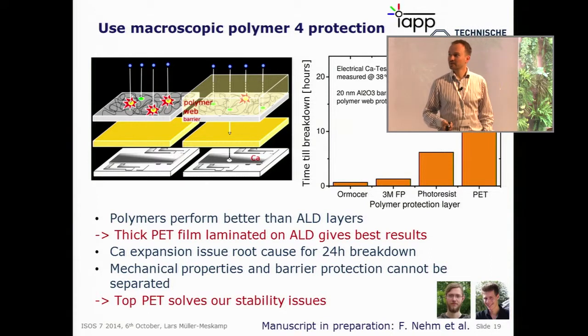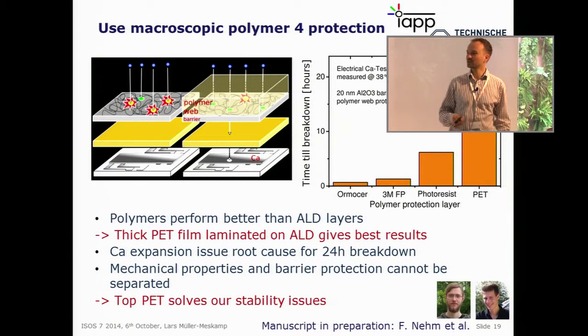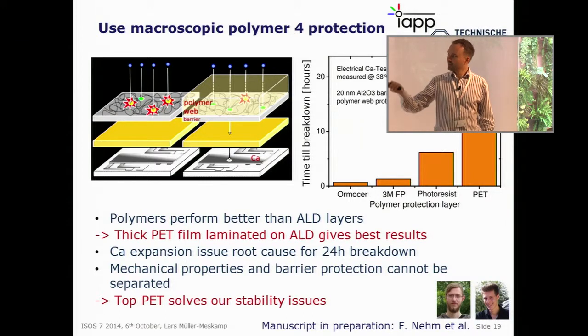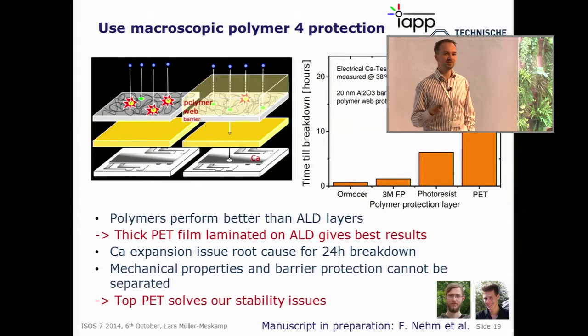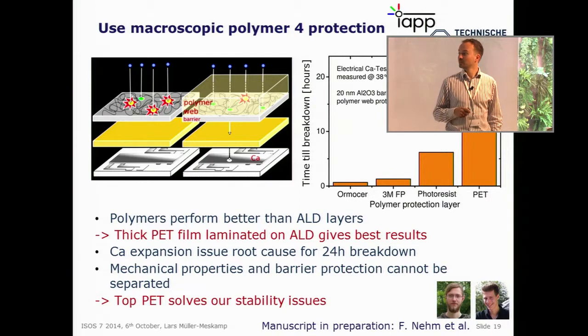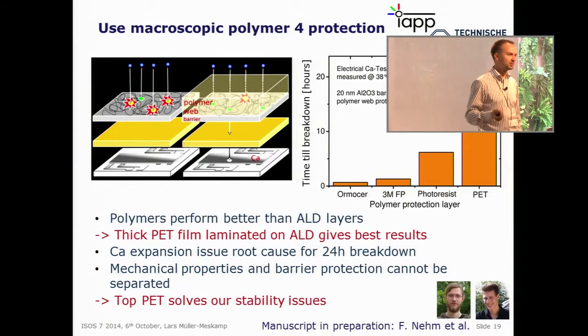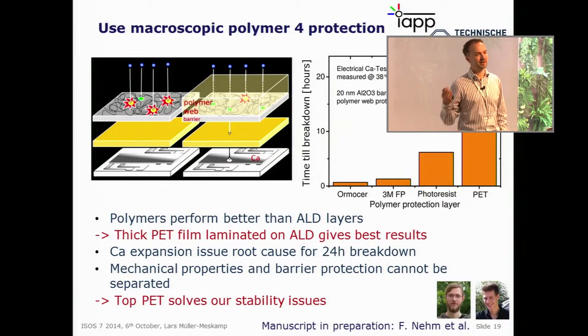But still, the time to breakdown is only 24 hours. Okay, but we can measure something. So actually, to laminate the thick PET on top solves all our problems. It greatly increases the stability of this. And this is what we do for all our measurements, since we have done this. In this case, the 24 hours are still caused because we do not have the decoupling layer of the C60 below. So if we add the decoupling layer and the PET on top, then this is stable. But that really shows how much you have to protect your barriers. Okay, and as we don't have the C60 here, probably we cannot separate the mechanical properties from the barrier protection.